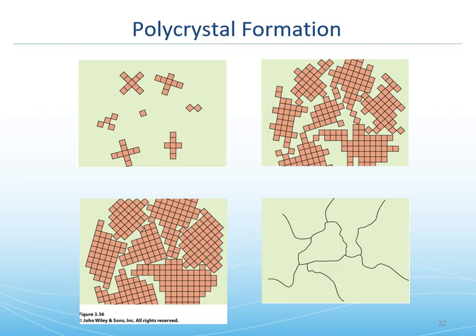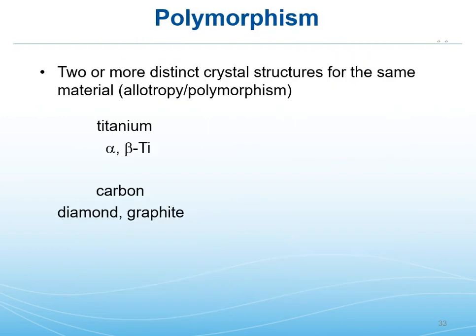Things don't quite line up, and so grain boundaries are, compared to the center of a grain, wide open. So they are higher energy, they have a higher void fraction in 2D, they're diffusion freeways. So if you need to diffuse something in, it will probably go in first along the grain boundaries. And these are things we'll take advantage of in especially metals processing.